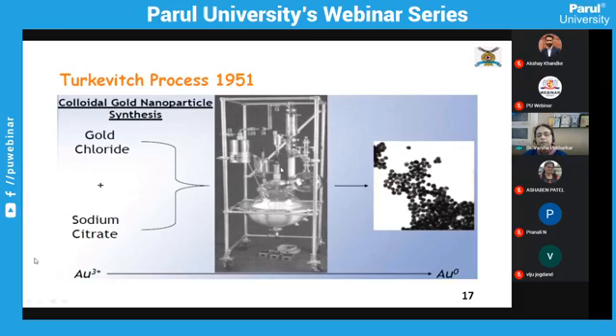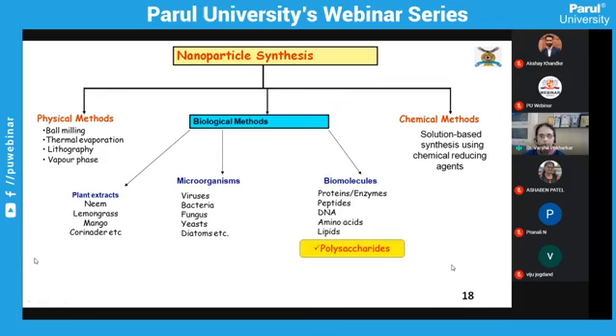So even in terms of technology requirement, there is nothing different that we require for preparing it. A simple reactor is good enough for preparing the gold sol. So the Au in +3 state gets reduced to Au0 state, resulting in the formation of these gold nanoparticles. As for the synthesis approaches for preparation of the gold nanoparticles, there are several approaches, starting from the chemical methods that we just discussed. These are the solution-based synthesis using different chemical reducing agents such as citrate or borohydride, etc.